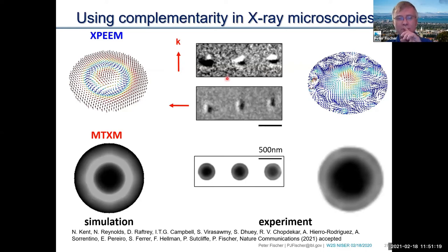I also want to mention here that the PEEM is of course only probing a certain projection, but when you rotate the disk and the system by 90 degrees, you can combine these and really retrieve a fully three-dimensional representation. And this is shown here. These are real experimental data, a fully 3D representation of the spin texture here, together with the MTXM down here. We were able to prove and demonstrate that, yes, we have seen a magnetic Hopfion in our designed magnetic multilayer, which was, I think, a big success because we started off from theoretical predictions. We had the pre-information from our target skyrmion, and we were finally able to prove by these complementary X-ray microscopy techniques that we are able to see a Hopfion.